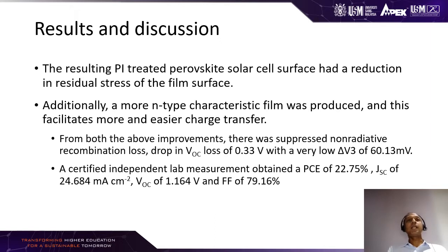millivolts. Now, a certified independent lab measurement obtained a power conversion efficiency of 22.75%, a current density at short circuit of 24.684 milliamp per centimeter square, a V open circuit of 1.164 volts, and a fill factor of 79.16%, which is a very high fill factor.